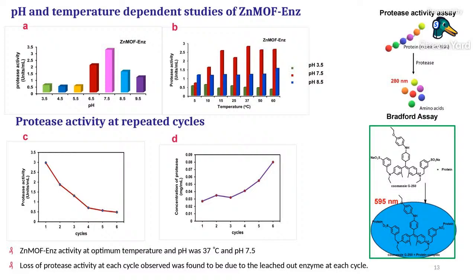So how can we do this process? What we did is we did the pH and temperature dependent studies of the zinc MOF enzyme, and we looked at how it behaves. We tried the protease activity at different pH levels, and what we found was that pH 7.5 is pretty good, and for temperature, 37 degrees is pretty good. Even at 15 degrees it is going well. So at pH 7.5, we can use it from 15 degrees up to 60 degrees.